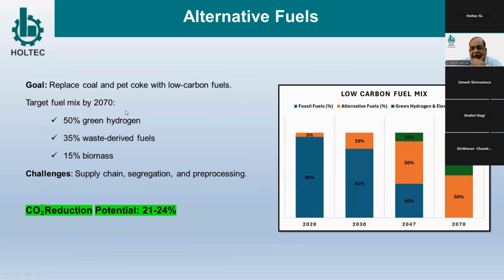The target mix for 2070 is 50% green hydrogen, 35% waste derived fuels, and 15% biomass. So you can see the shift from 95% fossil fuel to almost zero by 2070. And green hydrogen will be the player from 2035 to 2070, from 10% in 2047 to 50% by 2070. So this will be the fuels for the future.